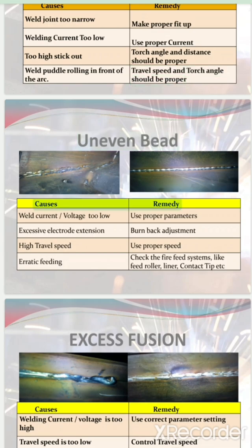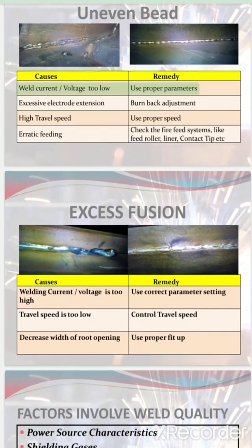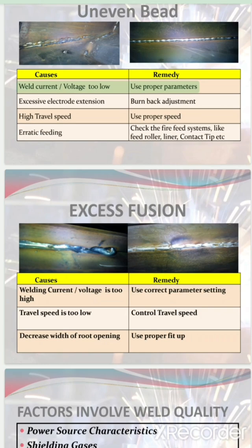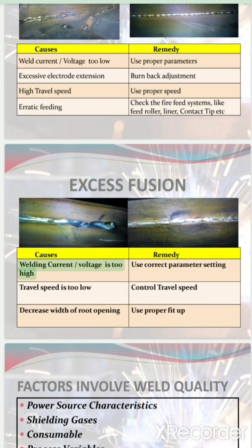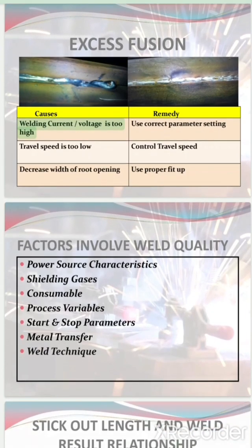Uneven bead. Causes and remedy: weld current / voltage too low, use proper parameters. Excessive electrode extension, burn back adjustment. High travel speed, use proper speed. Erratic feeding, check the wire feed systems like feed roller, liner, contact tip, etc. Excess fusion. Causes and remedy: welding current / voltage is too high, use correct parameter setting. Travel speed is too low, control travel speed. Decrease width of root opening, use proper fit up.